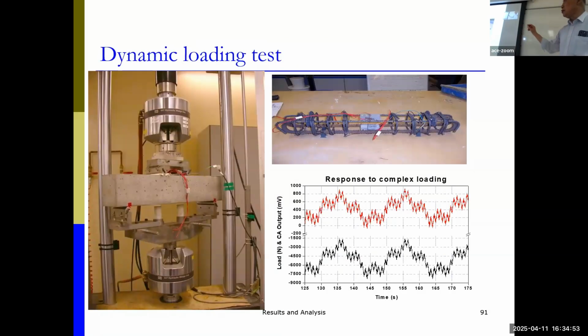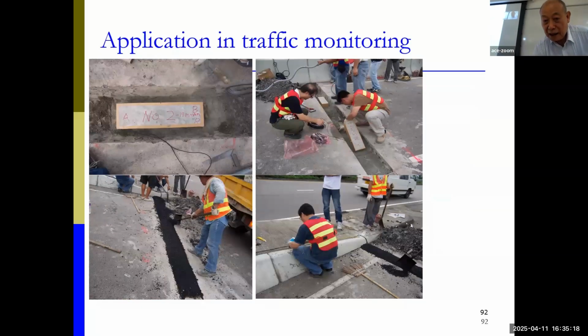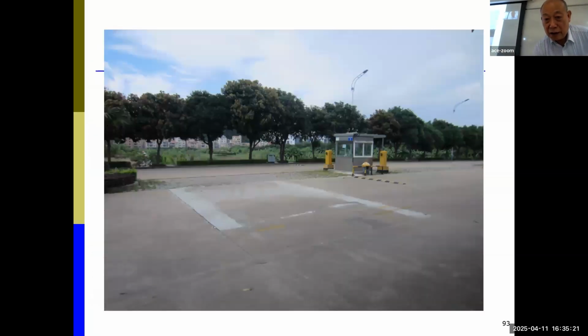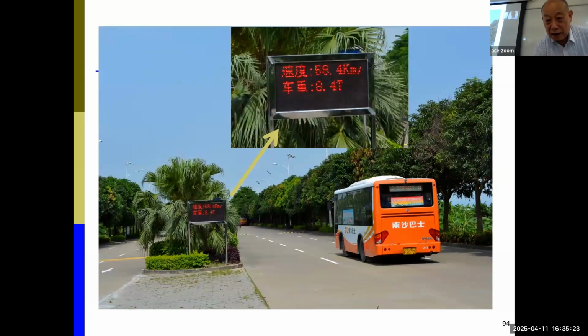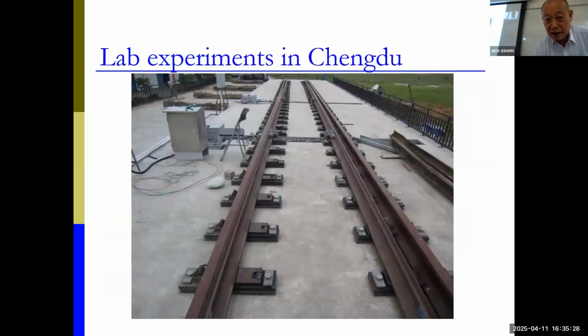We also put the transducer into a reinforced beam, and we used 4 different frequencies and 4 different amplitudes to generate this zigzag load pattern, and we found the transducer inside the beam can follow exactly the pattern of the loading. So that means it's very reliable. And we used that for highway traffic monitoring, so when a vehicle passes through, it can give the speed and the weight.